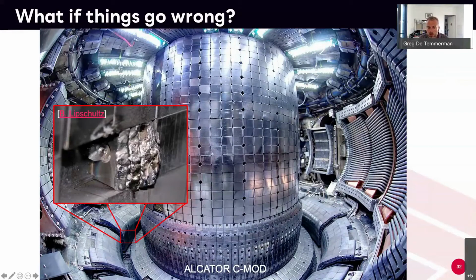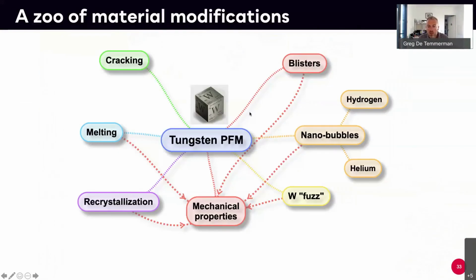Every time they would start the plasma, this was melting, ejecting tungsten all over the place, and this will not move. So what you can see here is you have plenty of tiles with discontinuous edges and so on, and again everything has to be shaped to be protected.